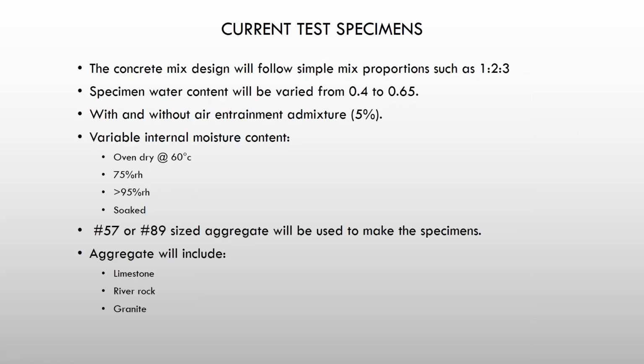The current testing we're going to be doing is using standard simple mix proportions for the concrete. Specimen water content will be varied from 0.4 to 0.6. We'll be doing tests with and without air entrainment. And we're going to vary the internal moisture content: oven dry, 75% relative humidity, 95%, and soaked. We're going to be using number 57 and number 89 size aggregate to make the specimens. The aggregate will be either limestone, river rock, or granite.